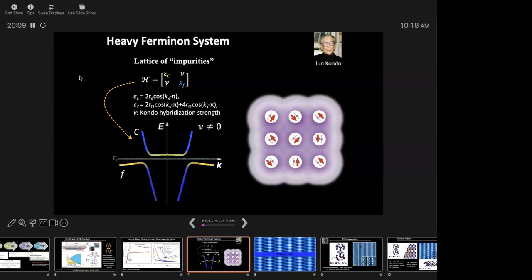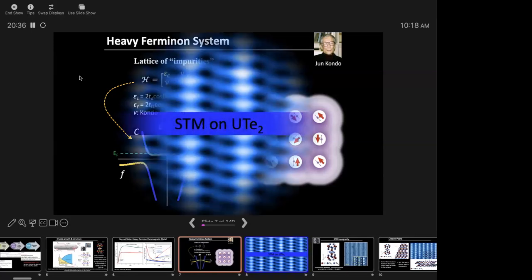And depending upon whether your Fermi energy is in the middle of this gap, in which case it's an insulator, or it intersects one of the bands, you have a metal. And in the case of uranium ditelluride, the Fermi energy intersects the conduction band, and you have a metal. So it's actually a heavy fermion metal. However, with this extremely large density of states sitting right next to the Fermi energy, which is important to note.